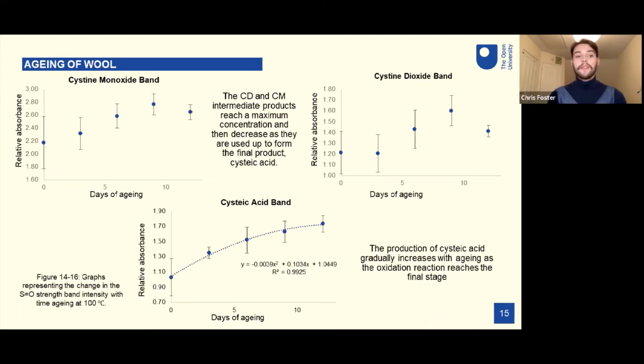And these graphs show days of aging along the x-axis, where the day corresponds to how long it's been in an oven at 100 degrees Celsius. So I've done 0 days, 3, 6, 9, and 12. And then along the y-axis is relative absorbance, and this is essentially the intensity of the band. So it correlates to the amount of that product there is.